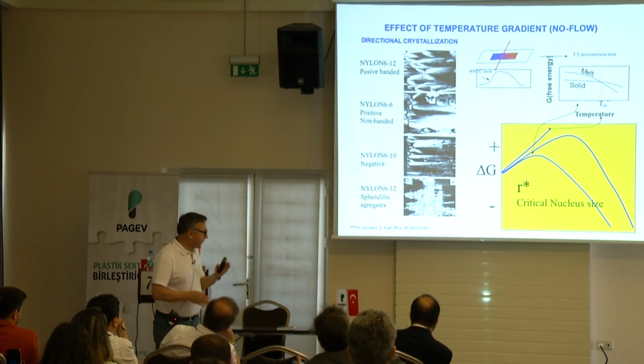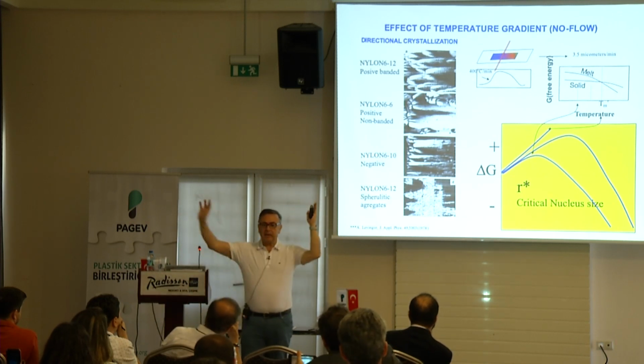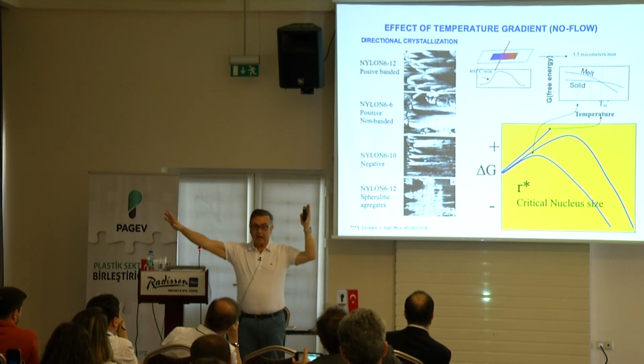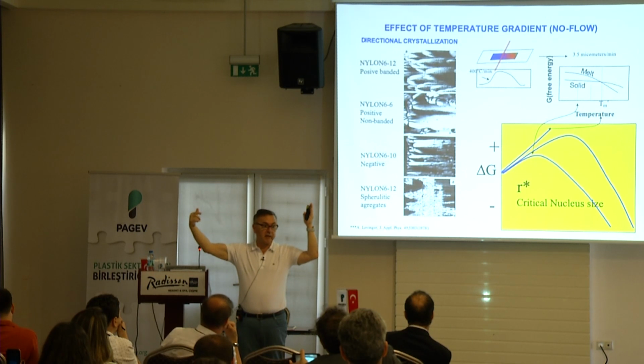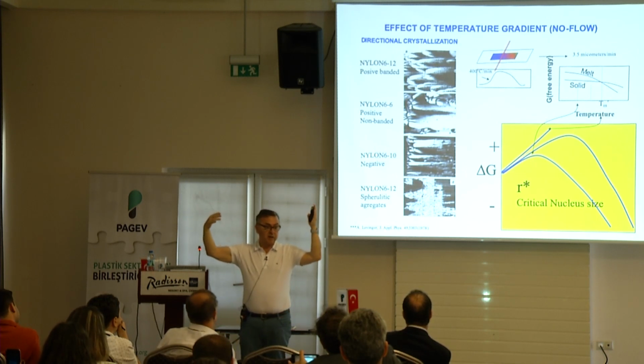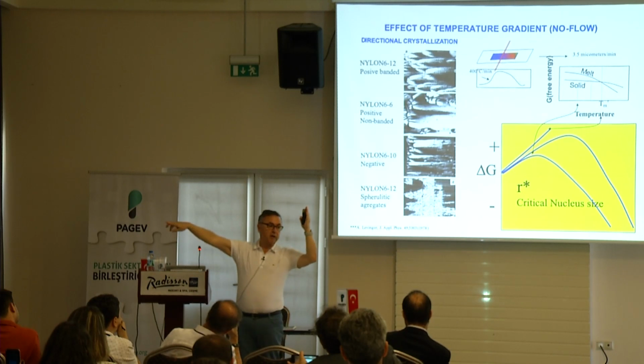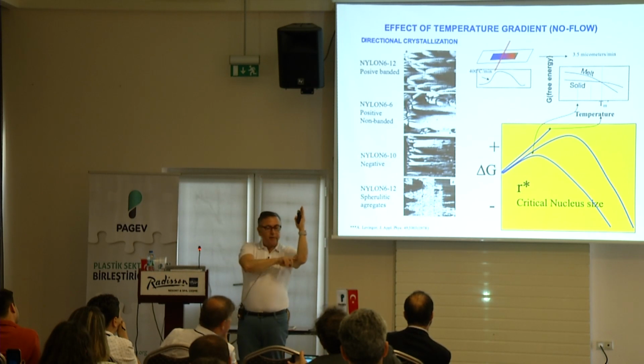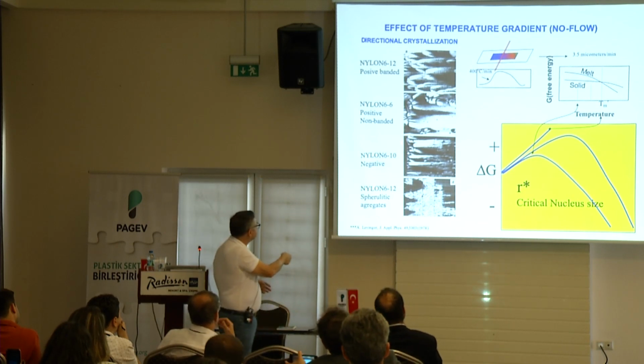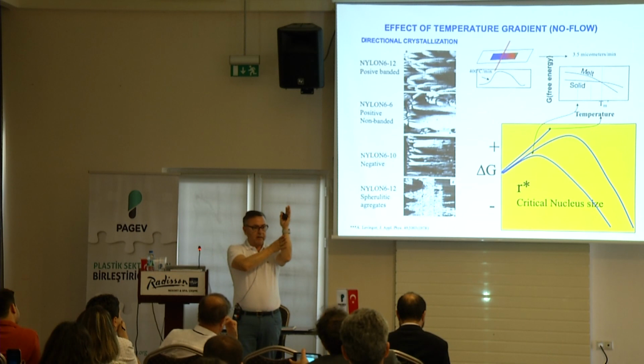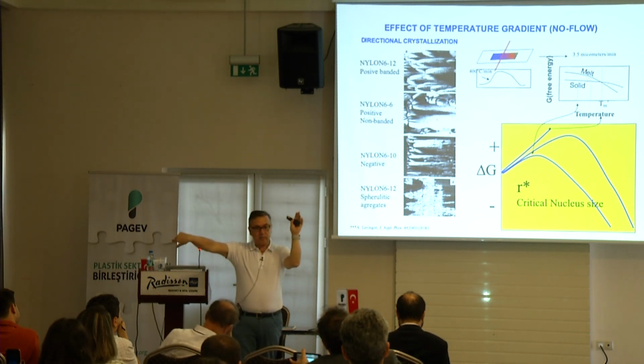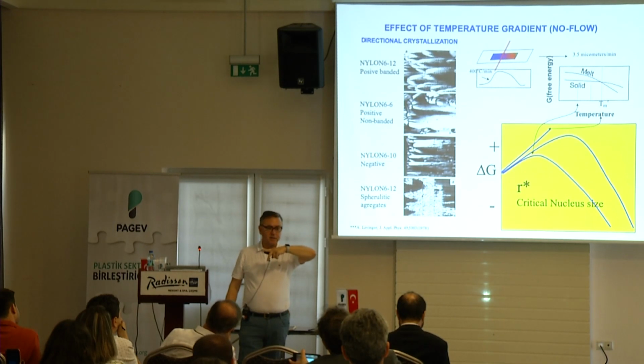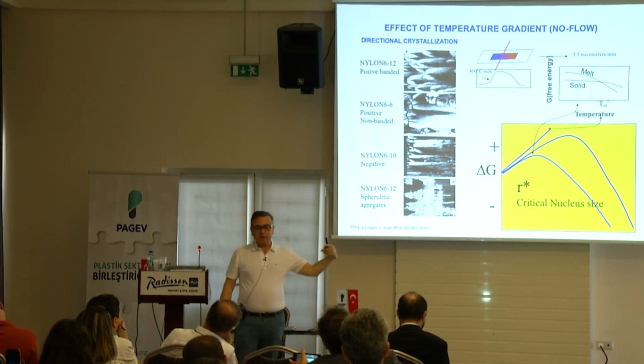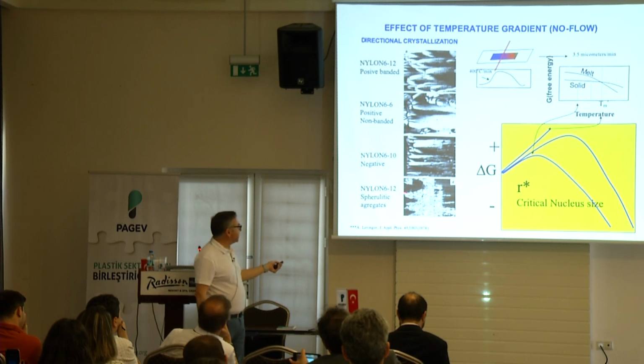Okay? But if I have a surface here that is cold, but inside the molten material that's still hot, and our material says, I'm not going to give up my heat so easily because my thermal conductivity is poor, right? So I have a temperature gradient. So what happens? You have a whole bunch of nuclei formed. They can grow relative to each other quickly, and then they bump into each other, and they're done. The only option that they have is going inside. So this is called directional crystallization. The materials start crystallizing inside, and you create these kinds of structures.